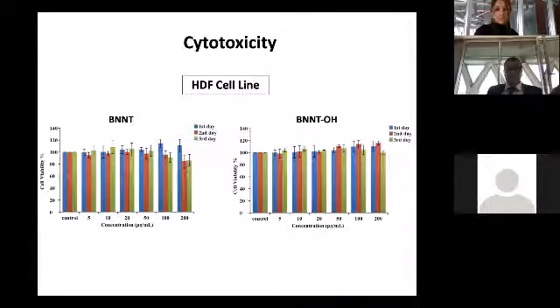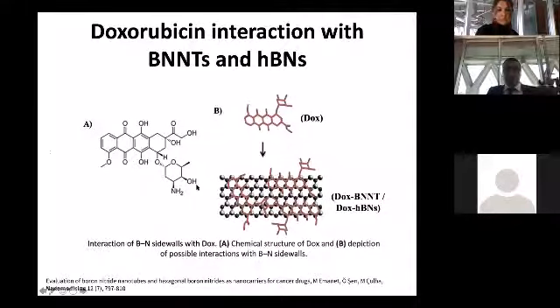We modified boron nitride nanotubes and actually introduced hydroxyl groups through boron atoms. So, as you see, they are not toxic. Actually, we are not the only ones claiming that this material is non-toxic. Of course, the dose is important here. If you put too much, and also their hydrophobicity could introduce some tricks, because it's not easy to disperse this material in culture medium.